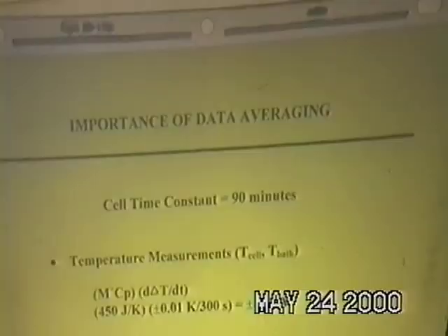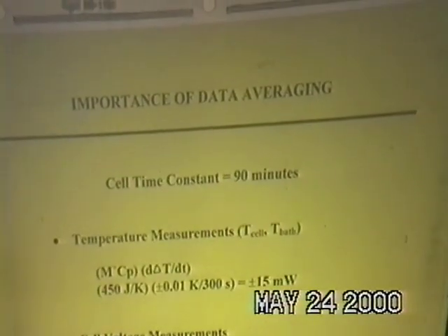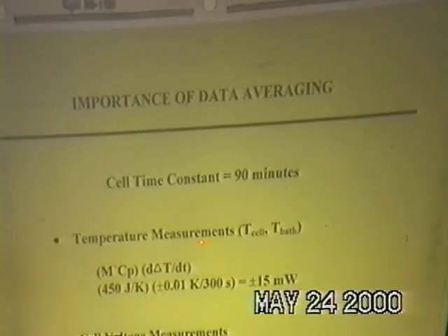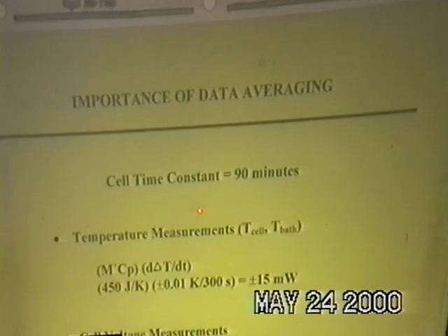Now the time constant of the Fleischmann-Pons calorimetry is about 90 minutes. Therefore, you need to average the data. I want to point out, if you don't average the data and take one data point, some error sources. The heat capacity of the water equivalent of the cell is 450 joules per degree. If you have an error in measurement from one point to another of only 1/100th of a degree, and multiply those two together, the data is taken every 300 seconds, you see an error of plus or minus 15 milliwatts.